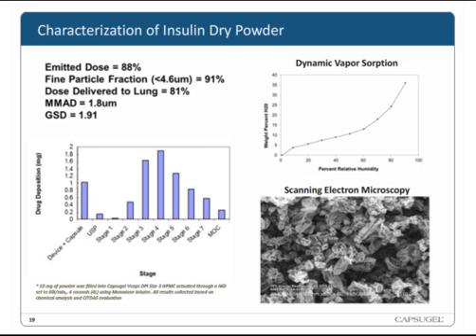The calculated dose delivered to the lung was very high, and we achieved our 2 micron mass median aerodynamic diameter and geometric standard deviation. And then, this was work that was done here at Bend to make sure that we weren't sending to Lovelace anything that we didn't think Phil and his team could handle in terms of the animal model. And then once at Lovelace, with their aerosolization methods that were more appropriate for the model Phil will talk about, they confirmed these results.